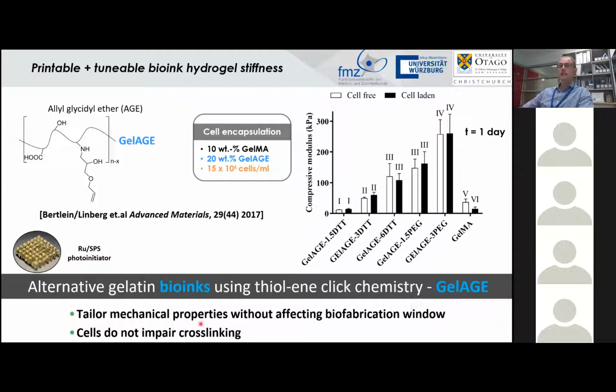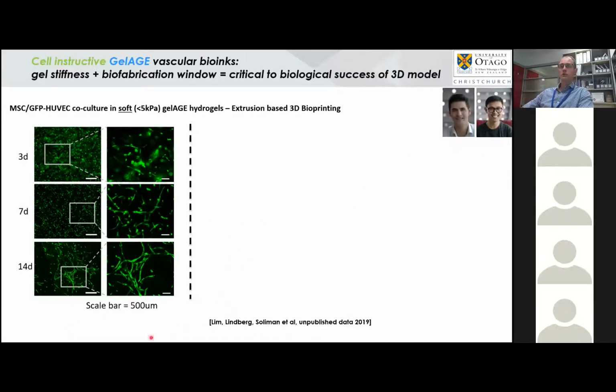The interesting thing is that we could then show that with the incorporation of cells, because of the step growth polymerization, cells didn't necessarily affect any of the downstream properties or disrupt the cross-linking mechanism. In our hands, at least, we've observed quite a reduction in the properties you achieve with GelMA in the presence of cells, which of course is not what we want. So, some quite nice tunability properties.